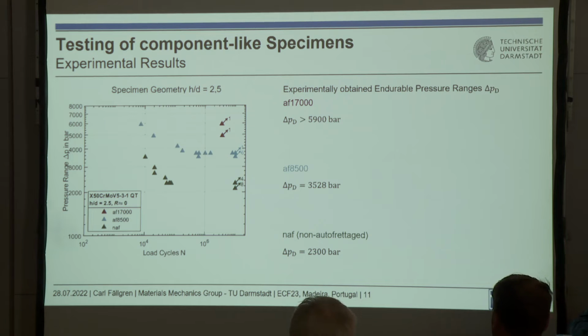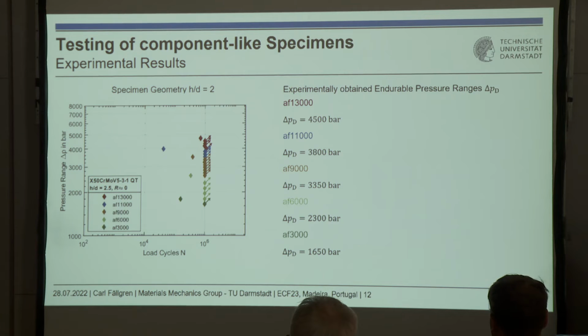And for 17,000 bars autofrettage, we only produced runouts, because in this case the endurance limit of the testing equipment was not as high as that of the specimens we had. So the endurable pressure range is approximately higher than 5,900 bars. For the other specimens, which we tested in the pressure raising technique, for 3,000 bar autofrettage, we had 1,650 bar endurable pressure range, and so on. And you see all those arrows indicate runouts, and the last failure we had at 4,000. This is something above, so 4,500 was the last endurable pressure range we could achieve with a fully autofrettaged thinner specimen.